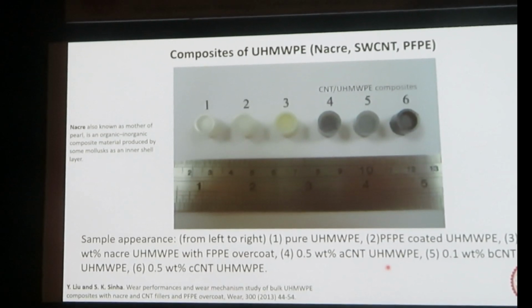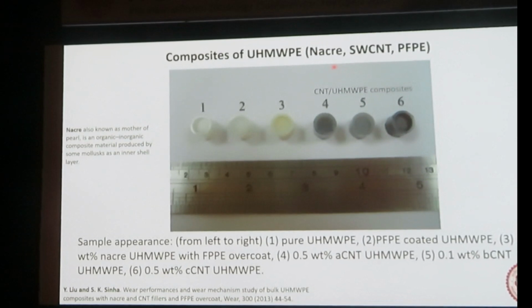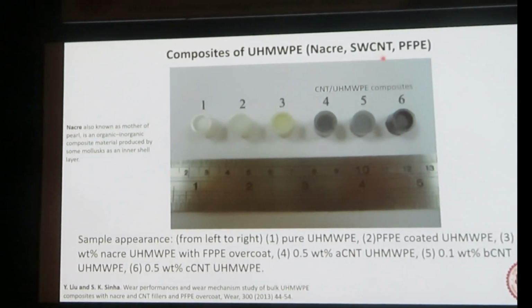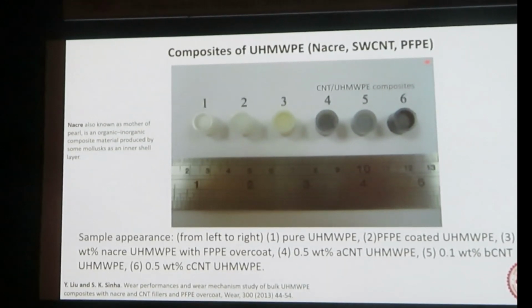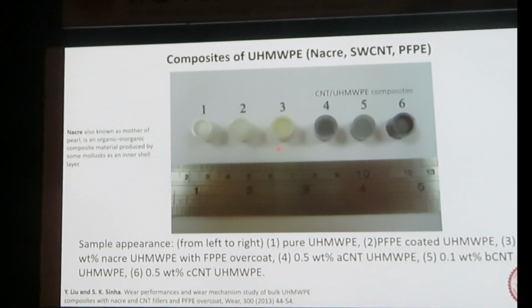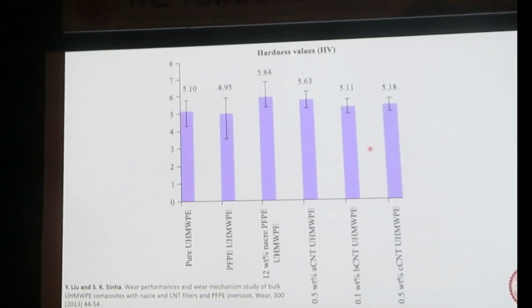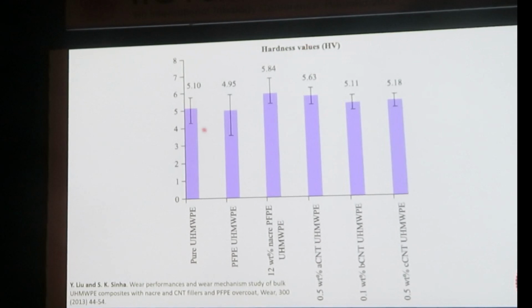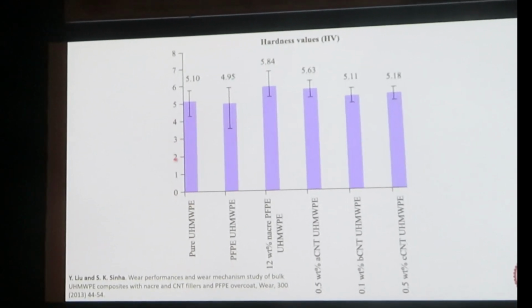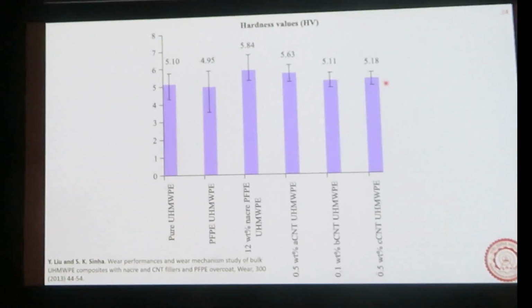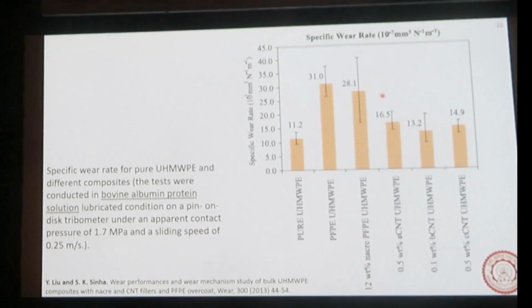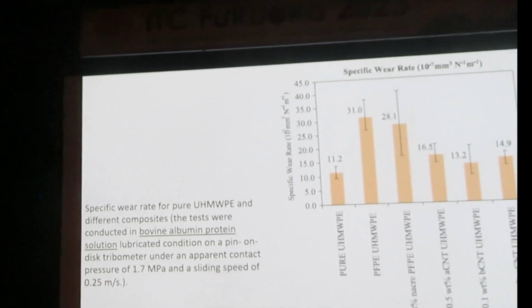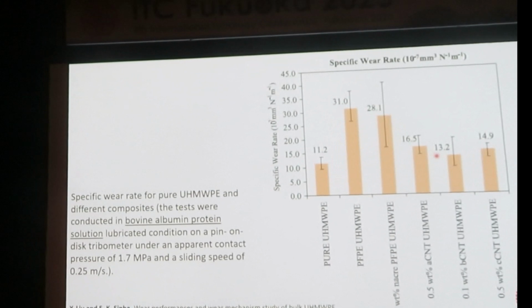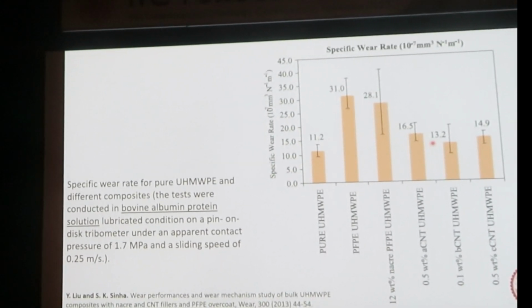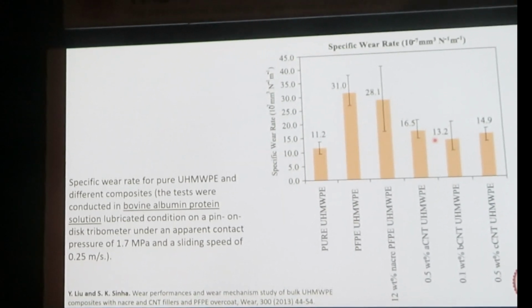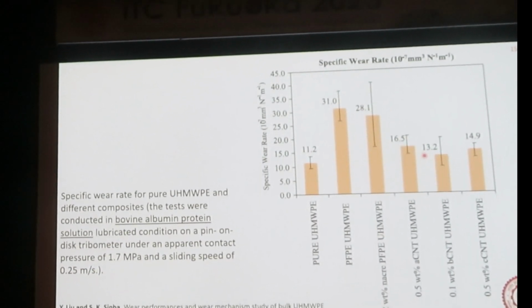Some other composites have been tried, and this is from our work, where we tried nacre, which is from the seashell, as well as single wall CNT, and also adding PFPE, which is perfluoropolyether. This is in liquid form. We mixed them in UHMWPE in different proportions, and the results are, for example, in hardness tests in a dry condition, the hardness is slightly better compared to pure UHMWPE, which is here. So as you add these kinds of particles, you improve the hardness. But in terms of specific wear rate, we hardly got any improvement. This is a little older work, 2013, but still quite relevant. We understood that making a composite like this perhaps is not helping, because UHMWPE is already very wear resistant, and making it further wear resistant was not possible.